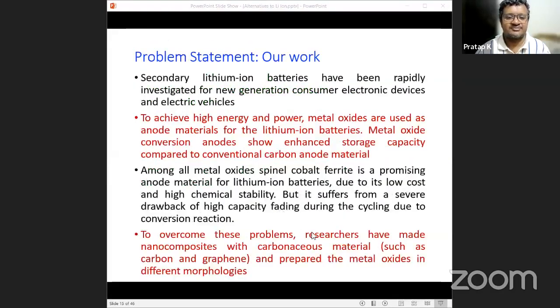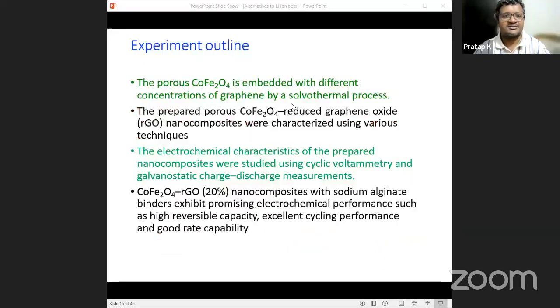So to overcome these problems, we have made a composite of carbonaceous materials and cobalt ferrite. So we have fabricated in different morphologies and all this. So this is our experimental outline. So we have fabricated porous cobalt ferrite, embedded with different concentrations of graphene. Means initially we started with pure cobalt ferrite. We have added 10% of graphene into it. That is the second sample.